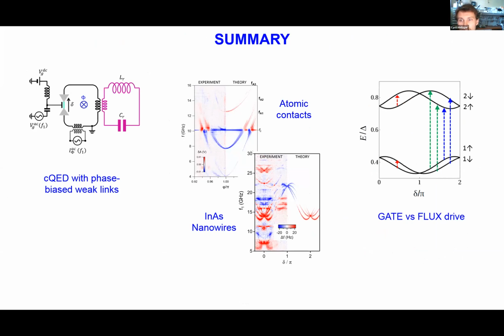With this, I'd like to conclude. So we've presented a theory that was able to describe the coupling of a resonator to a multi-level system of Andreev bound states. And we have applied this theory to experimental data. In the case of atomic contacts, everything is analytical and quantitative agreement is reached. And for indium arsenide nanowires, in the general case, it's less straightforward. But still, with this theory, we were able to understand and capture some features of our spectrum, like the effect of curvature. And I also discussed the effect of driving the system either through gate or through flux and the existence of spin selection rules.